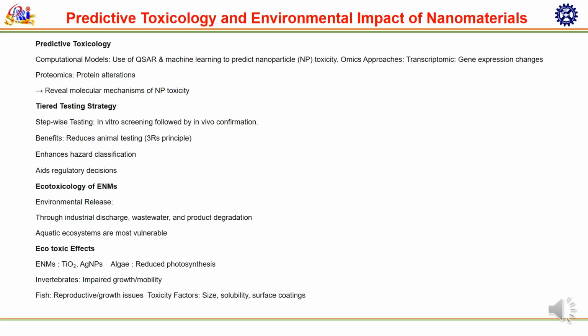Ecotoxicity of nanoparticles: environmental release via industrial discharge, wastewater, sewage sludge, and product degradation, with the aquatic ecosystem as the most vulnerable. Ecotoxicology effects by engineered nanoparticles, titanium oxide and silver nanoparticles: algae show reduced photosynthesis, invertebrates impaired growth and mobility, fish reproductive or growth issues. Toxicity factors like size, solubility, and surface coating, which we already covered in previous slides.